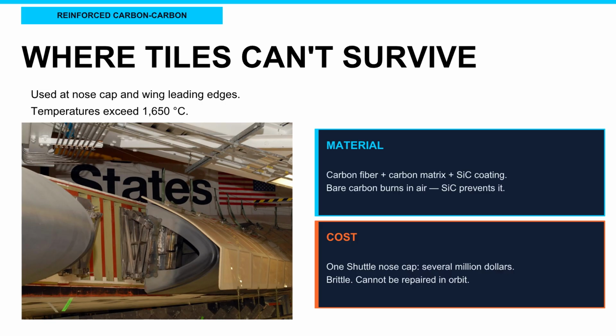Reinforced carbon-carbon is used where temperatures exceed what silica tiles can handle. On the shuttle, RCC covered the nose cap and wing leading edges, the highest heat zones, reaching 1650 degrees Celsius or above. RCC is a carbon fiber composite with a carbon matrix. Both reinforcement and matrix are carbon. The material is then coated with silicon carbide to resist oxidation. Bare carbon burns in air at high temperatures. The coating layer prevents that.